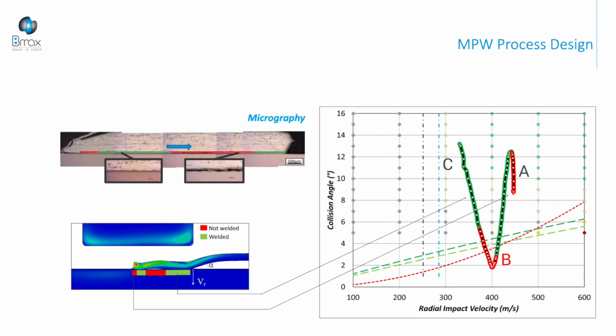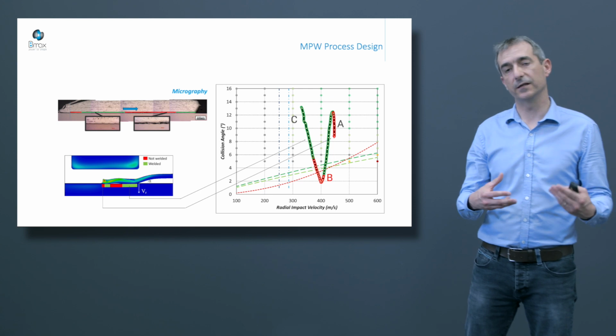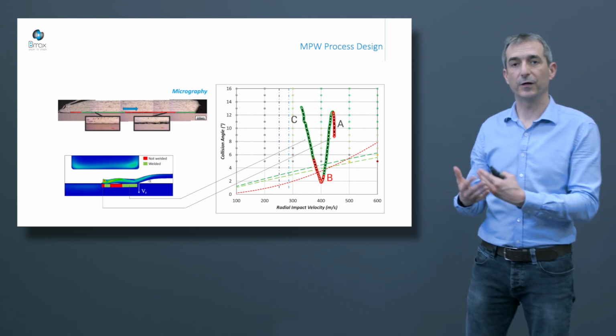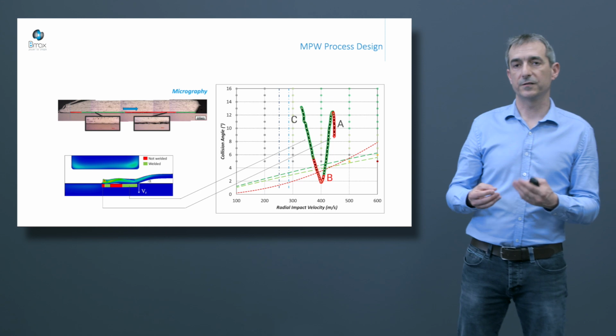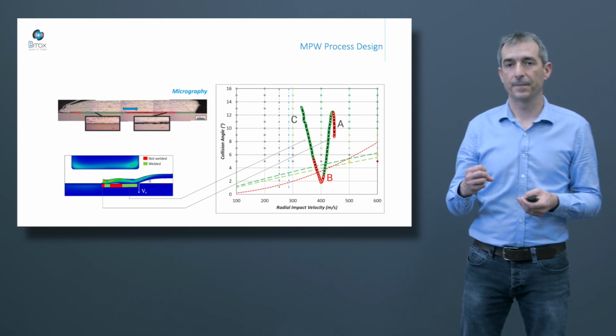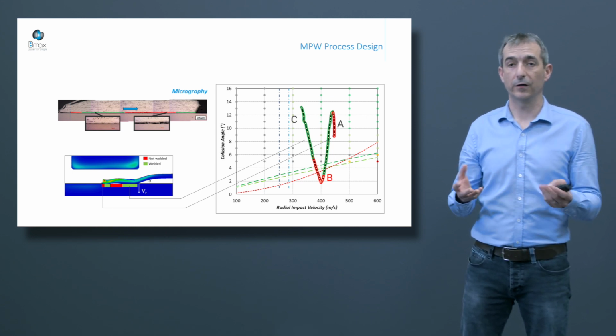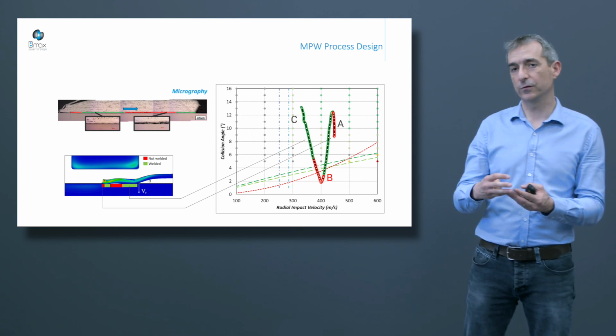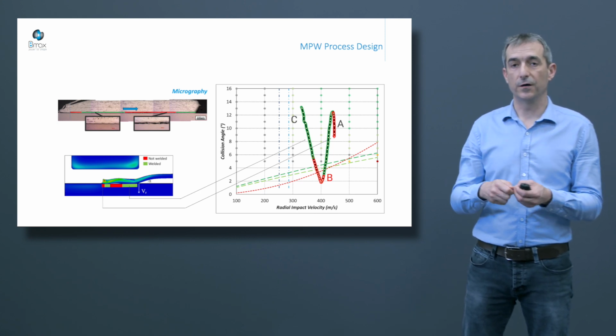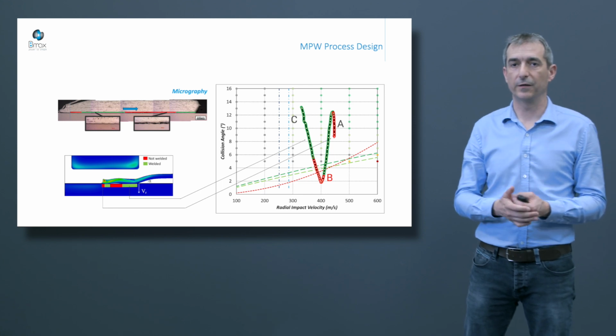After, we perform an experimental test, and we can measure by micrography the length of the weld done, and we can identify where the weld is good or not with green and red colors. And we project and transfer this data onto the numerical result in the welding window. And as you can see, at point A, we have no welding. It's normal because we have a delay. Even if we are in good conditions, we have a delay to create the intermetallic, for example, between dissimilar materials.